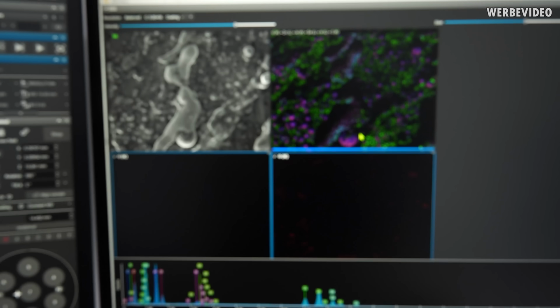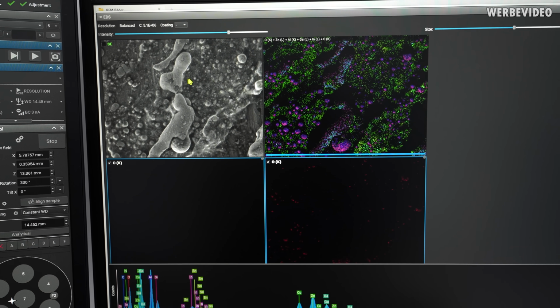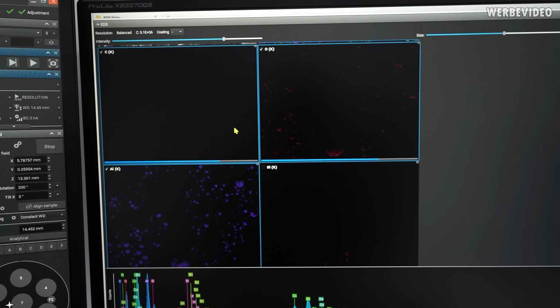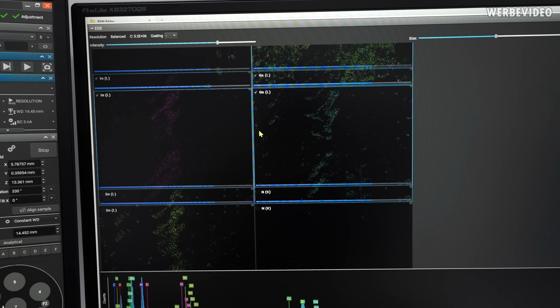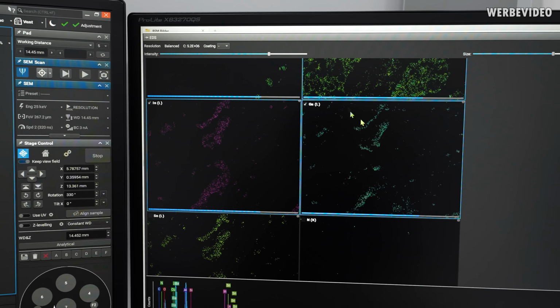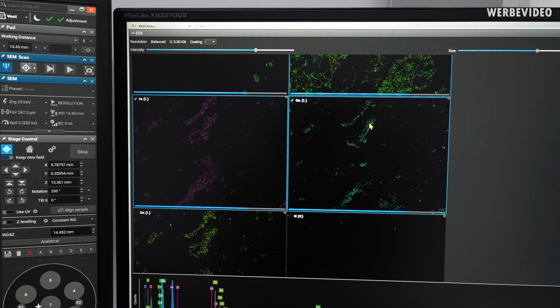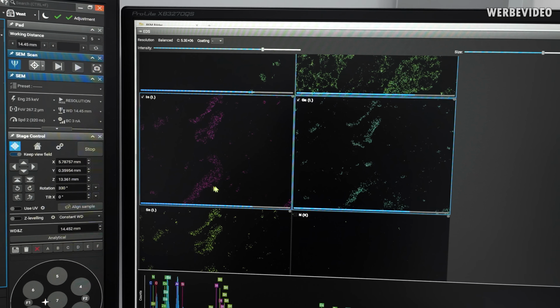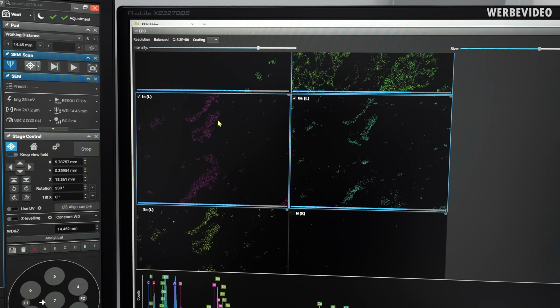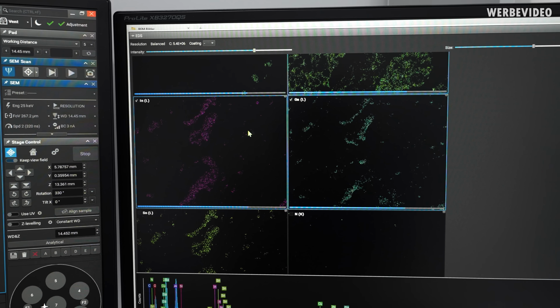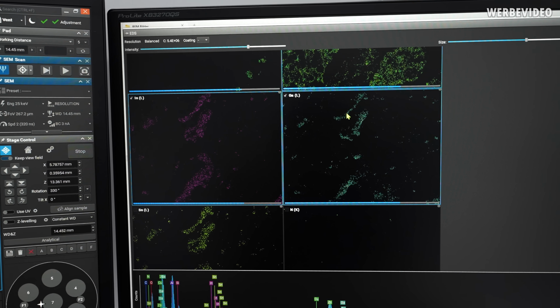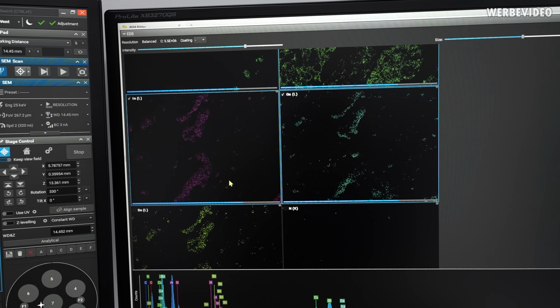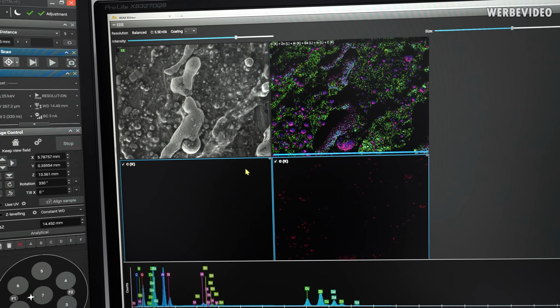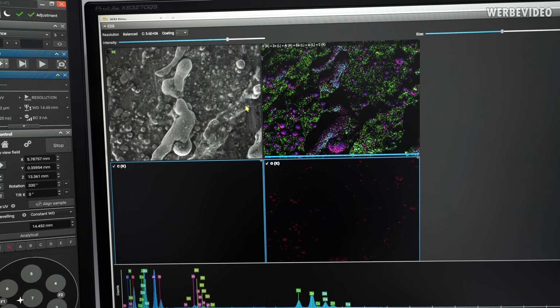And then just a reminder of how the image looked. So we have those structures in the center, and if we scroll down to gallium and indium, then we can clearly see that it just aligns with what we're expecting. These shapes together, gallium and indium, would form the liquid metal, and you can see that they're in the same position. Just confirms that we are seeing a liquid metal alloy here.